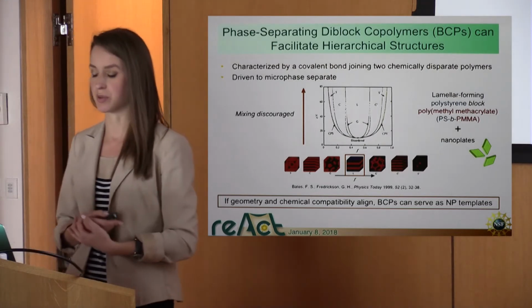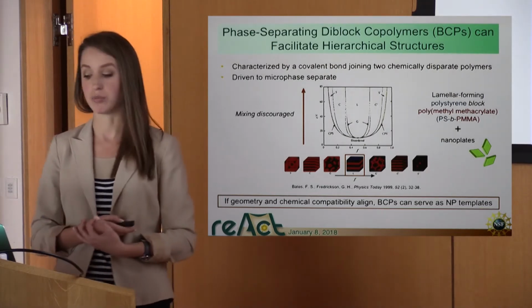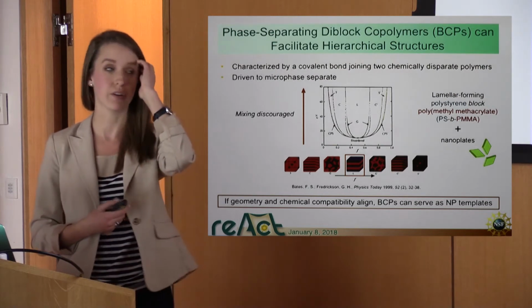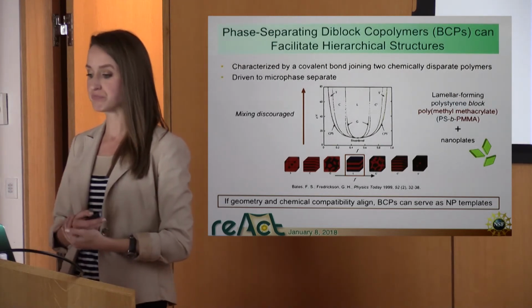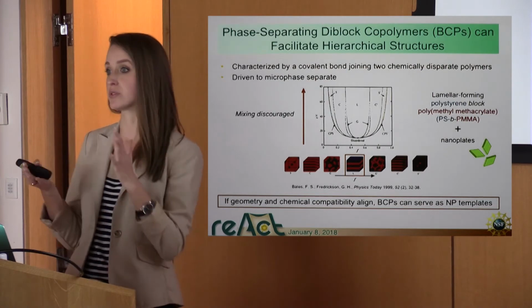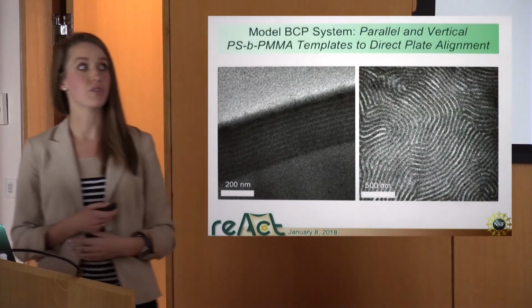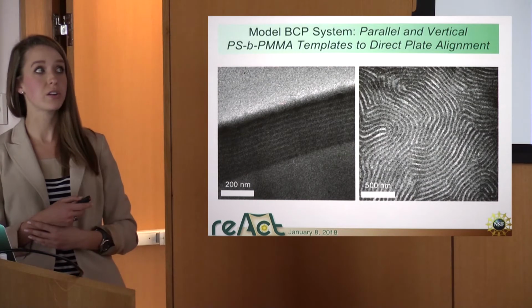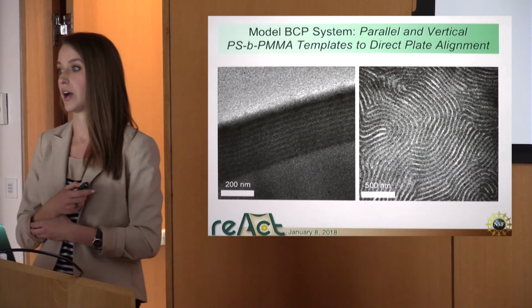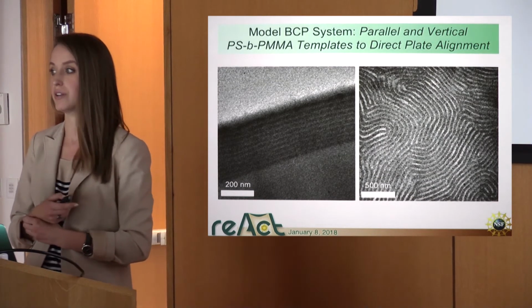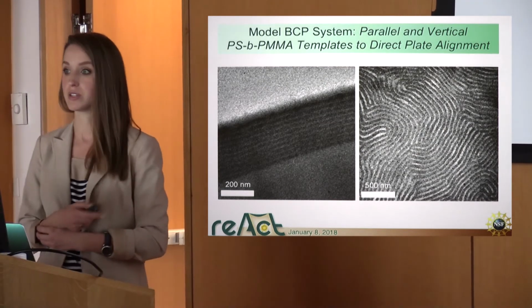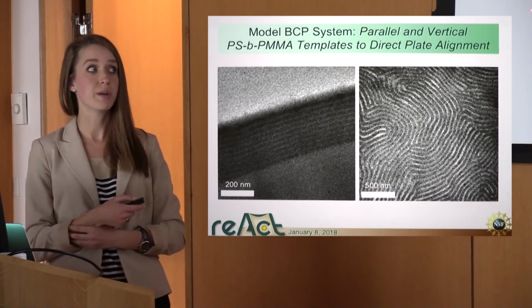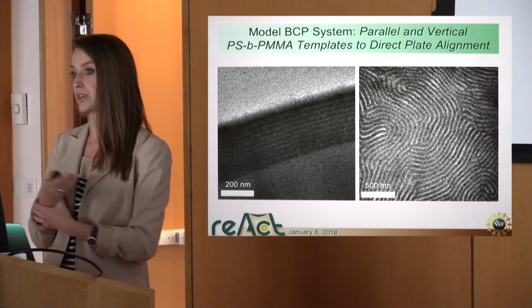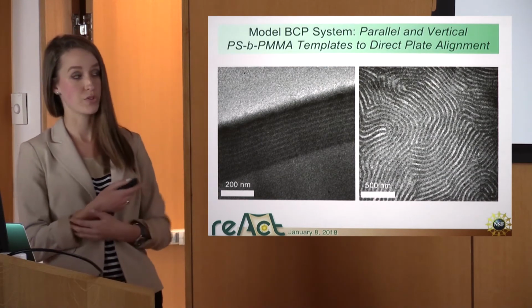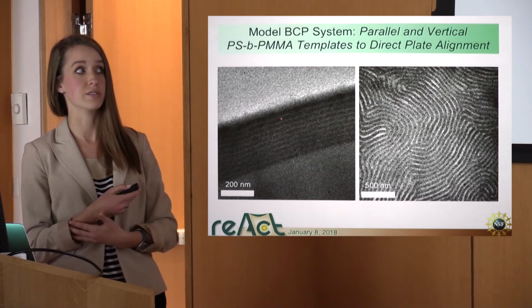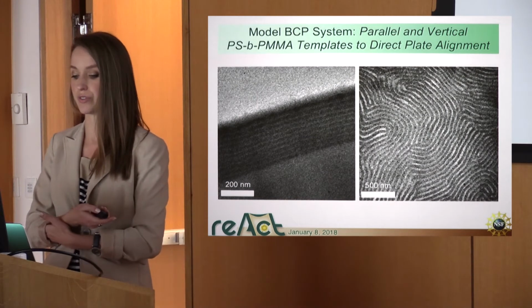So just to introduce my system further, I'm working with this model nanoparticle system and block copolymer system, and I want to achieve different modes of orientation of the domains. So I have established a parallel alignment of the domains. Here we're looking at a TEM image of the cross section of a block copolymer formed on a silicon substrate. The PMMA domain preferentially wets the substrate as opposed to the polystyrene, and we can create these lamellar features parallel to the surface.